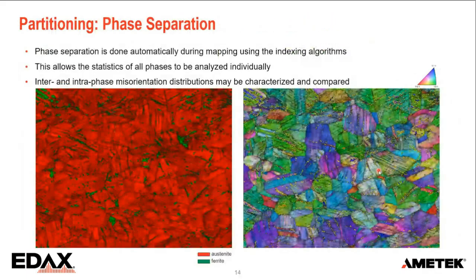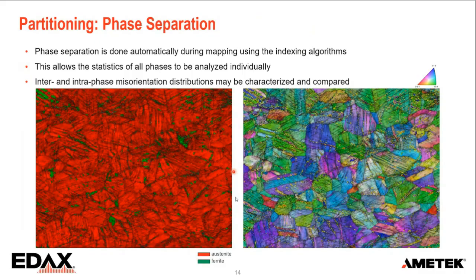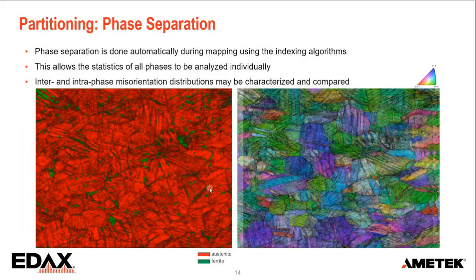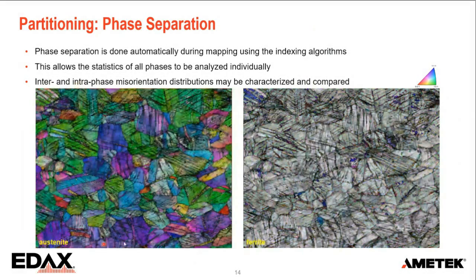And just to illustrate that, here is a duplex steel. So I have mostly an austenitic matrix, but there is some ferrite in there as well. And when we do a mapping, the software automatically indexes the patterns as either austenite or ferrite. And that will already give you this phase map. So nothing you need to do about that. But once you have this open in the software, you can separate them. So here on the left, I have my austenite fraction. Here on the right, I have my ferrite fraction.